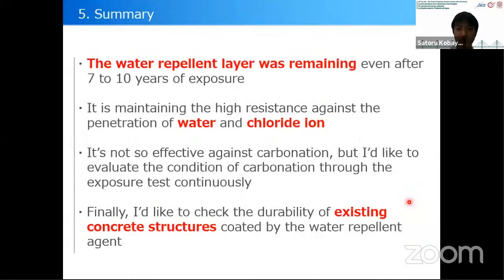It is a summary. As a result of the exposure test, it was confirmed that the water repellent layer was remaining even after 7 or 10 years of exposure, and it is maintaining high resistance against the penetration of water and the chloride ion. It's not so effective against carbonation, but I'd like to evaluate the condition of carbonation through the exposure test continuously. Finally, I'd like to check the durability of the existing concrete structure coated by the water repellent agent in the near future. That's all. Thank you for your kind attention.